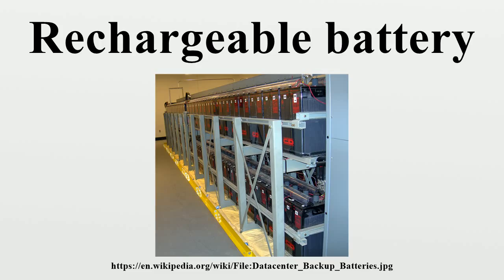Cell reversal can occur under a number of circumstances, the two most common being when a battery or cell is connected to a charging circuit the wrong way around, and when a battery made of several cells connected in series is deeply discharged. In the latter case, the problem occurs due to the different cells in a battery having slightly different capacities. When one cell reaches discharge level ahead of the rest, the remaining cells will force the current through the discharged cell. Many battery-operated devices have a low-voltage cutoff that prevents deep discharges from occurring that might cause cell reversal.